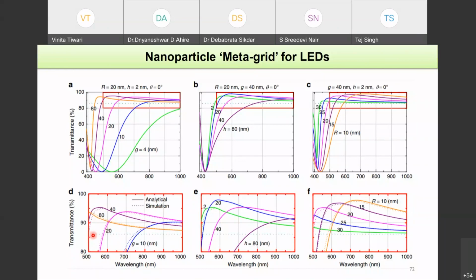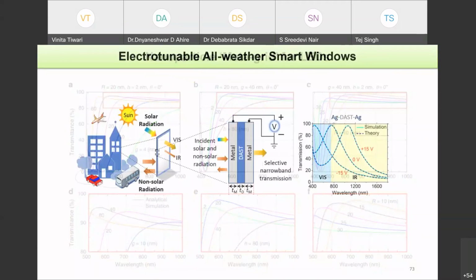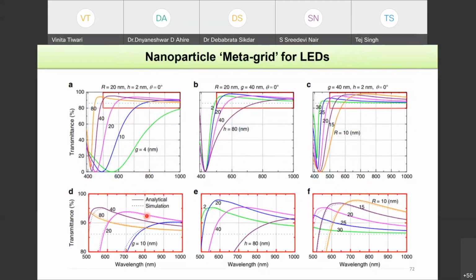And this is something interesting, that normally without the nanoparticles, you get only this much, which is 84, 85%, I think it's 87% of transmission. But with nanoparticles, you can go up to 95%, 96%. More calculations can be done, and optimization allows you to get this transmission level up to 99.9, or 99.5%. It means you can extract all the photons that are getting generated in the LED by using this nanoparticle metagrid. We have filed a patent for this. I hope the technology will be available soon for some commercial usage, but that is going to be a very interesting application of nanoparticle plasmonics, or you can say nanoplasmonic metamaterials, for a practical application like enhancing light from LEDs.